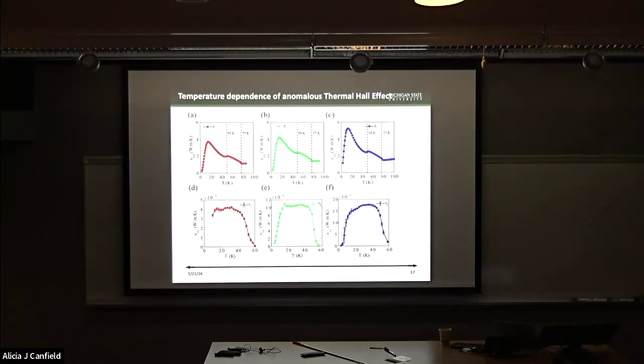Now, coming to Martin's question, we tried to reproduce the measurements on many samples. Here are some of them, and you can see the thermal conductivity and the temperature dependence of the thermal Hall signal. The other features are very similar, except the magnitude is slightly different. For instance, for sample one, the magnitude of the thermal signal is much smaller. The reason is that sample one is really the first sample that we measured.